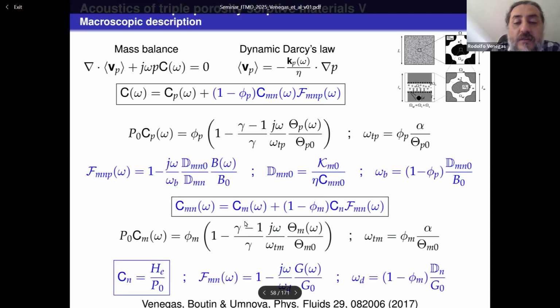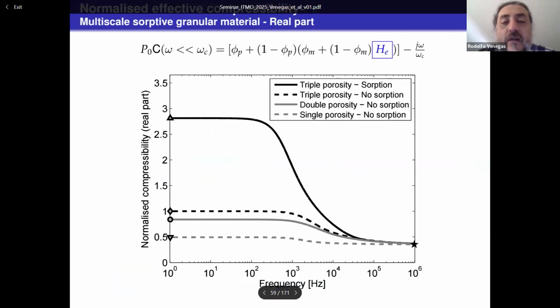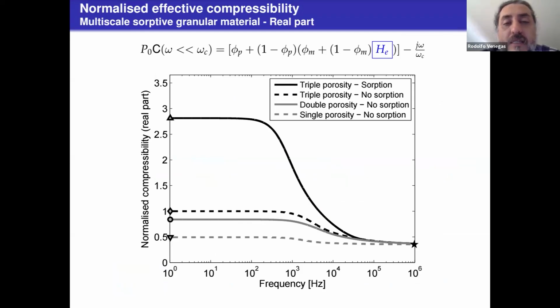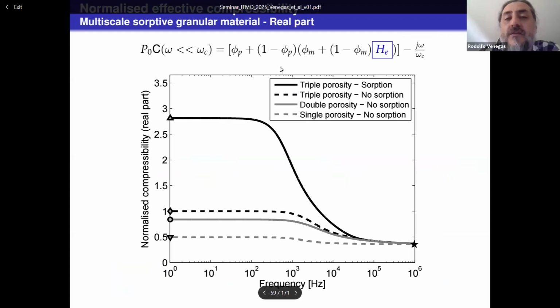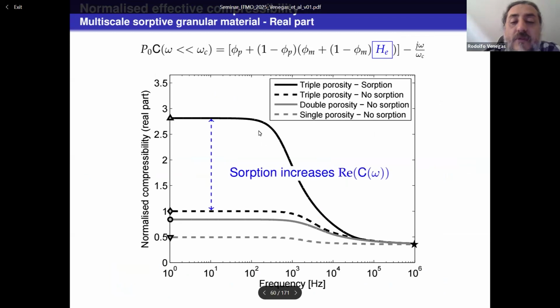So the general form, now we have already seen that CMM takes this form, and this is the general model that we have published in Physics of Fluids in 2017. In terms of results, the normalized effective compressibility is largely affected by this sorption phenomenon. So if we do an asymptotic analysis at low frequencies, we see that it depends on HE. And for a triple porosity material with sorption, the compressibility is very large. So sorption increases the real part of the compressibility in comparison with, let's say, a triple porosity with no sorption or other materials, as shown here.